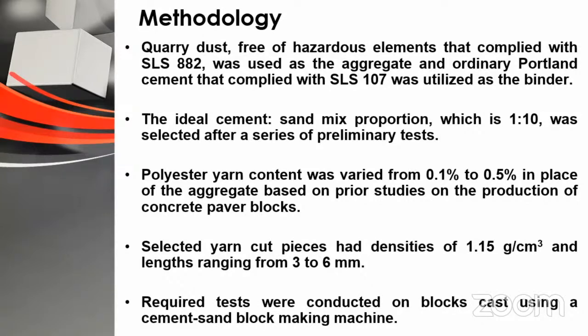In place of the aggregate, polyester yarn with a content ranging from 0.1 to 0.5% was used, based on earlier research on the creation of concrete paver blocks. Selected yarn pieces range in length from 3 to 6 mm and had densities of 1.15 gram per cubic centimeter. Blocks made with a cement sand block forming machine underwent the necessary testing.